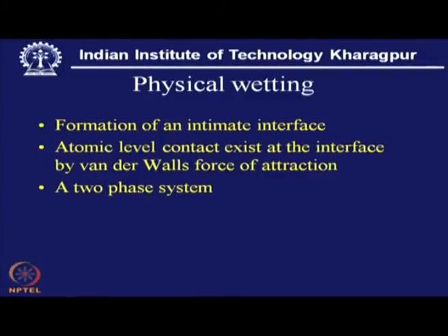Now, physical wetting. So far in the discussion we have made, the governing equations, whether it is Young's equation or Dupre's equation or a combination of that, are the guiding equations. What we have observed here is that the basic requirement is formation of interface and intimate contact to have the wetting.